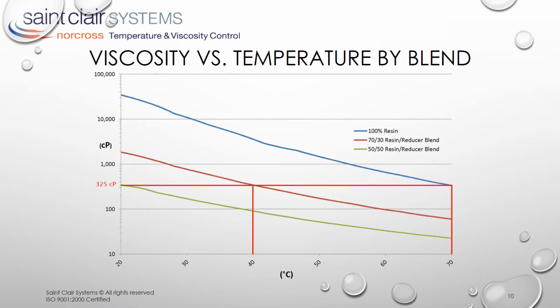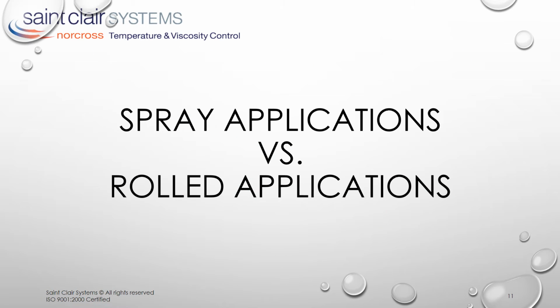At the extreme, the 100% resin is at 325 centipoise at 70 degrees C, and it could be used without reducer at that temperature, but this is too hot and requires special system design considerations to protect both the parts and the operators. Having defined the similarity and interaction between viscosity and temperature for modern coating materials, we can now turn our attention to their impact on the two most common application processes, spraying and rolling.